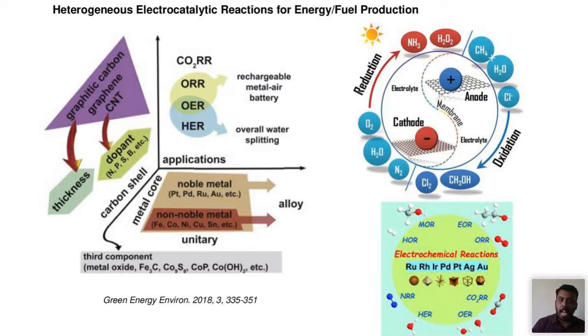So the thickness and dopants. Dopants means heteroatoms. You can use a non-metal like nitrogen, boron, phosphorus, sulfur. By introducing these heteroatoms into the graphitic structure of the carbon material, you are inducing some change in the electronic configuration, and also you can introduce some defects. Because of that, the electrocatalytic properties or the conductivity will change. So the carbon supports or carbon materials are used as electrocatalysts.